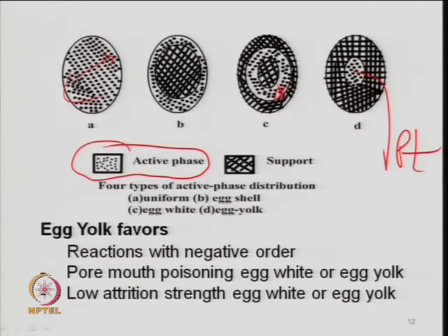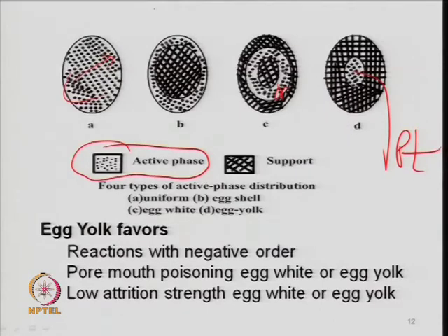One thing is the rate of drying; at that time I was talking about the rate of drying, but the same thing can be controlled by selecting a proper concentration of the acid, HCl or citric acid. If you have a high concentration of HCl or citric acid, then you will get a phase like this or like this. Everything is going inside, so it will make just a thin layer inside. When it is a thin layer, again your dispersion will go down. High dispersion may be in this case, because here it is uniformly distributed, but in this case it is just deposited in a thin layer. So, the problem may be that dispersion may be low. This may be one consequence of this acid concentration.